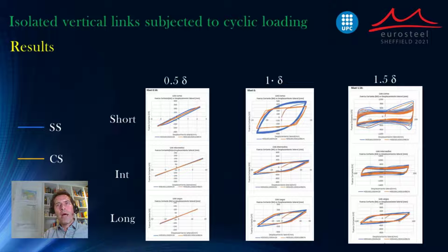And for the case of 1 times delta, we can see that in general, stainless steel, which is the blue curve, outperforms the orange curve, which is a comparable carbon steel. And then for the case of 1.5 delta, there is a clear difference between the cyclic behavior when it comes to very high levels of loading compared to the cyclic behavior when it comes to the maximum capacity obtained in the global response.